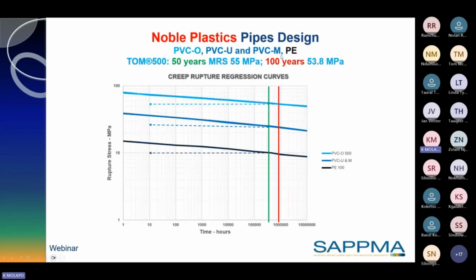So here you have different PVCs. The O, which has a higher strength. So you have O500. You also have PVCU and M, modified and unplasticized. And then at the bottom you have HDPE. So to get that 100 of HDPE, which is PE 100, you look at the green vertical line, which is 50 years on the log scale, and then the red one is 100 years. So you go to where your PE line crosses the green line. You will see, if you were to draw an arrow, the bottom arrow pointing to the left, you get a value of 10.